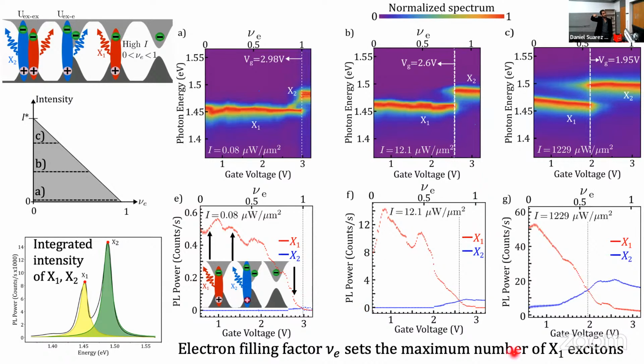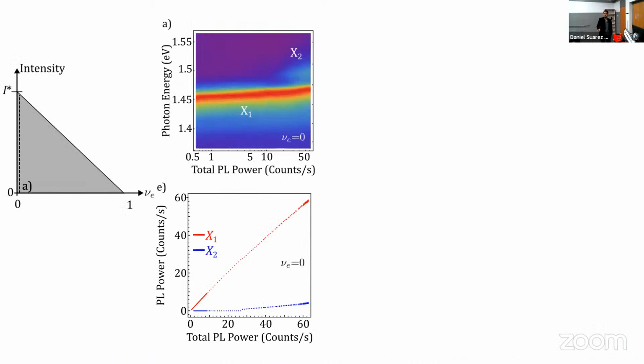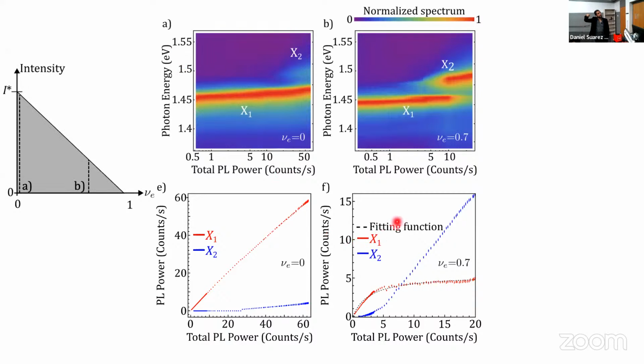Then we can have this for different intensities, and every time this takes place at lower and lower gate voltages. So the electronic filling factor sets the maximum number of excitons in empty sites that we can collect photoluminescence from. We can also do the opposite, fixing the number of electrons in our material and then tuning the number of excitons. So in this case, for example, we start again from an empty site, and we can achieve the formation of doubly occupied sites optically. If one sets the filling factor to 0.7, which means that 70% of the Moire sites are full with one electron, and 30% of them are free, then this is the situation. And if one analyzes the behavior of the photoluminescence intensity, one will notice that it actually saturates as one increases the number of excitons in the material.